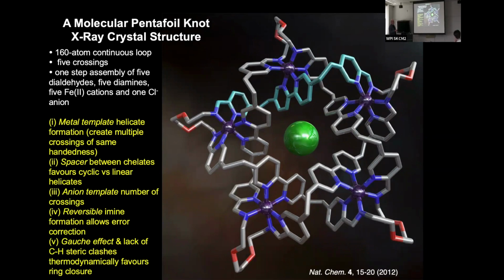So first of all, you need to have this metal template helicate formation. It needs to be a helicate because that creates the crossing points that all have the same handedness, and you need to control the handedness in these crossing points so that it goes over under each time. So the metal template helicate formation is crucial.